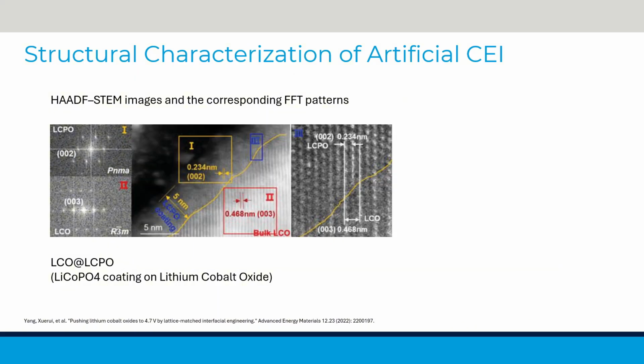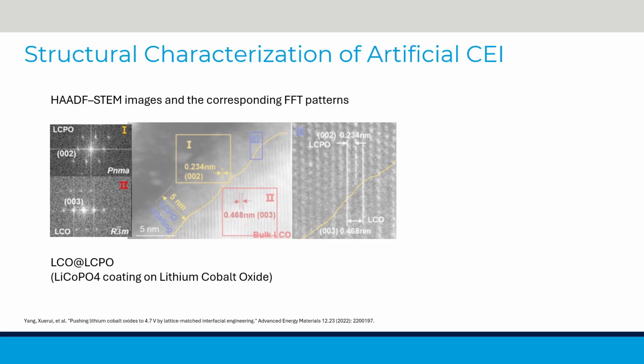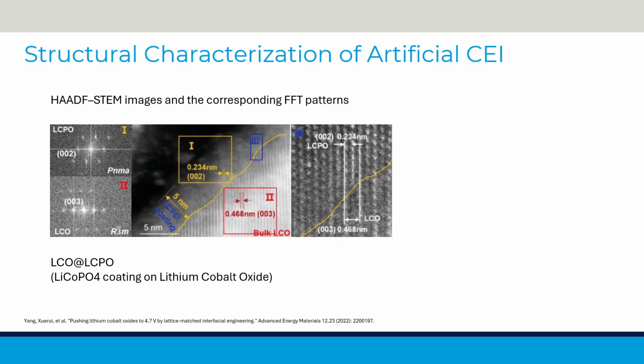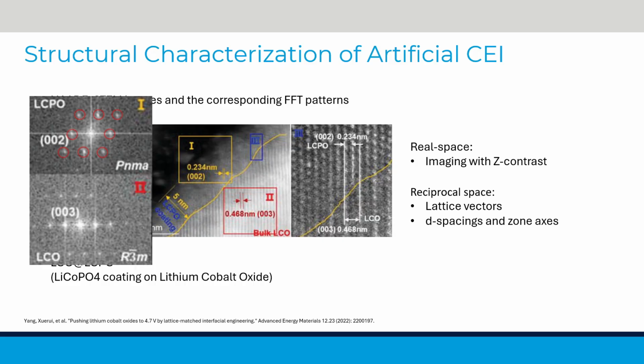HAADF-STEM imaging combined with an FFT pattern can quickly provide qualitative or semi-quantitative crystallographic insights. This high-angle annular dark field mode gives real space images with Z contrast, which is useful for detecting compositional variations. Applying a fast Fourier transform converts this image into reciprocal space, revealing periodicities that correspond to the projected lattice spacings of the crystal. Bright spots in the FFT represent reciprocal lattice vectors, whose positions yield d-spacings and zone axes.